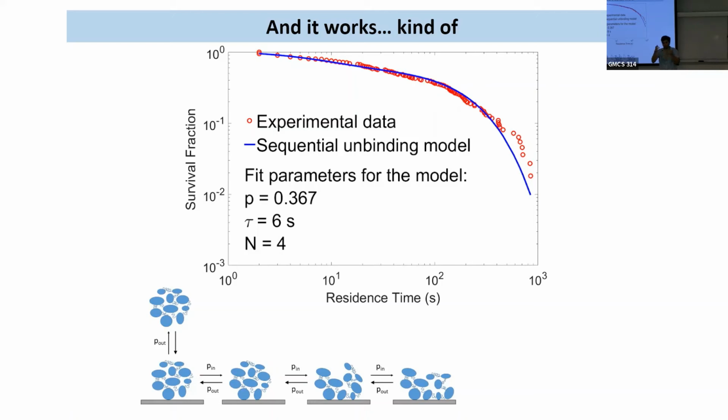Now, if I want to rip off, I can't rip the entire structure off. It's like a zippering problem. Basically, I form one bond at a time because the other bond didn't have the space to access the site, but this one has formed, now this one can access, and then the next one can access as it sort of unfolds. And so you can have this 1D process. You cannot jump over. Maybe you can, but the energy barriers are quite high to do that. That's the energy of unfolding the protein. It's not completely unfolding, but the small conformational changes in the protein as it comes to the surface.